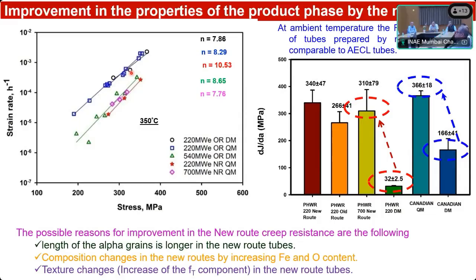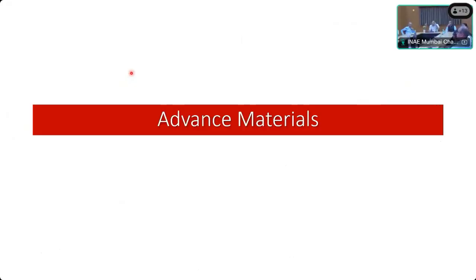As a consequence, on the right side you can see the fracture toughness, which was 32 in the first tubes made. It is damn low. Now, after all this modification, we have reached 310, which is very close to Canadian quadruple melted. So I suppose the 700 megawatt tubes will perform far better than the old tubes. We made them for 30 years, and they should survive 30 years. Keep your fingers crossed. We also changed several things in the composition. I don't want to go into those details. The size of the alpha grains and small changes in the texture, many such things were done along the way. So with this, let me take you to the next stage of the reactors.